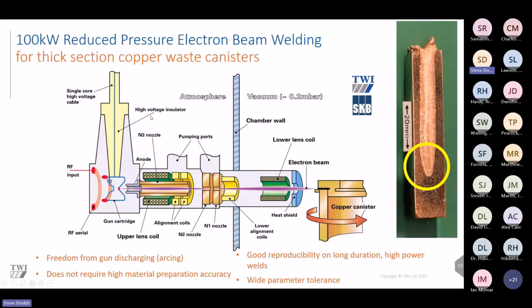So TWI helped develop a reduced pressure electron beam, and instead of 10 to the -4, 10 to the -6 vacuums, this is to the 0.2 millibar vacuum. What we've effectively got here is a much more production friendly system, which allows for significantly less vacuum downtime or even local vacuum around the canister head. Also, it allows for a slightly broader beam, which can also be wobbled around. Sorry for the untechnical phrase, but that means we're able to round out the root of the electron beam weld to offer a more gradual change in microstructure around that point region.